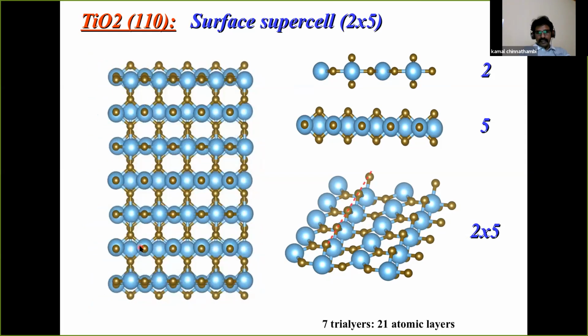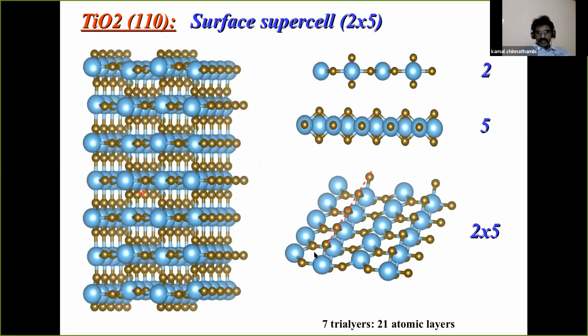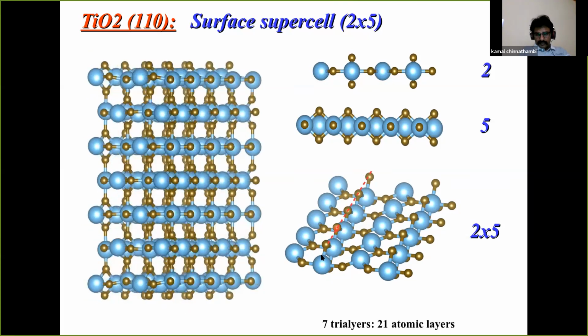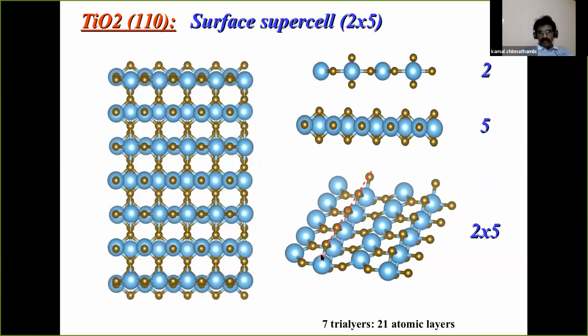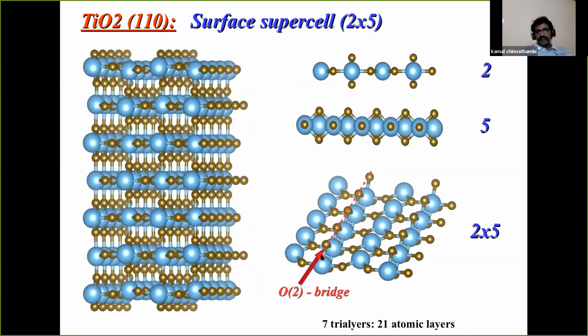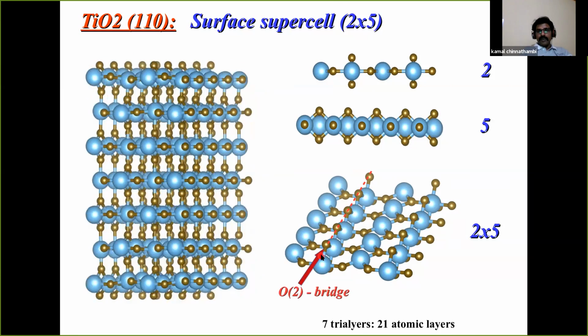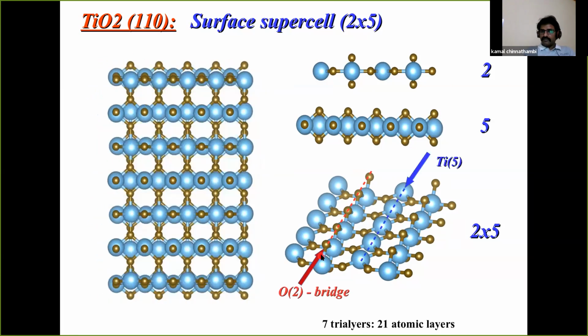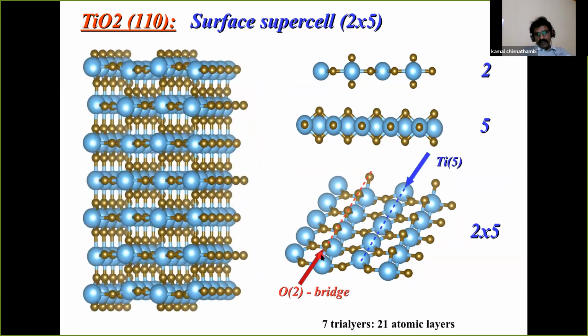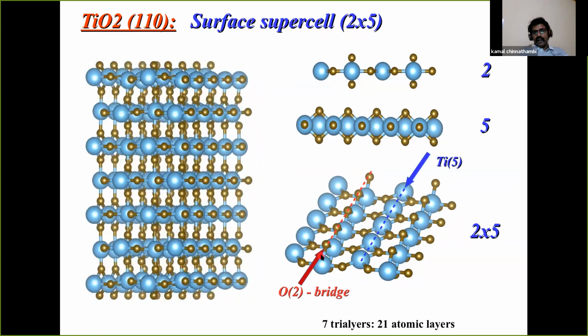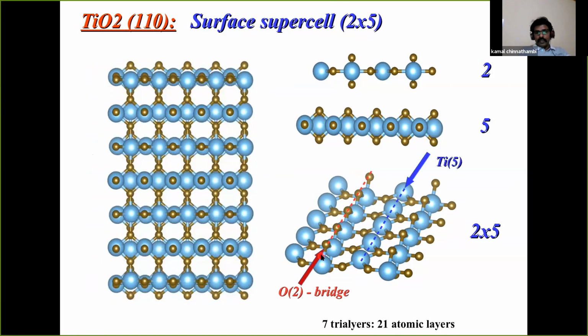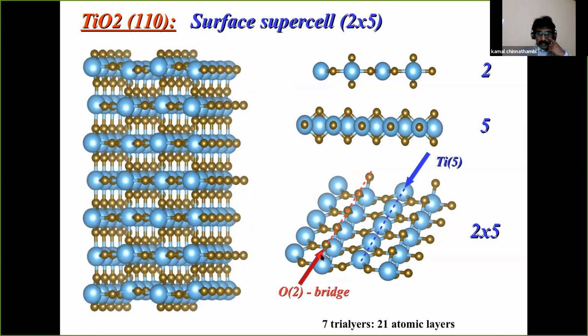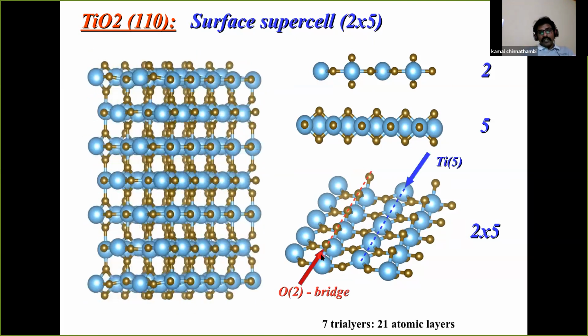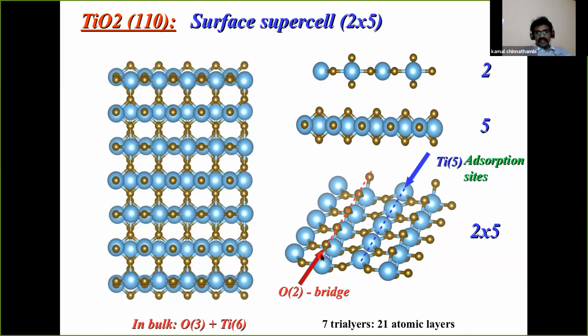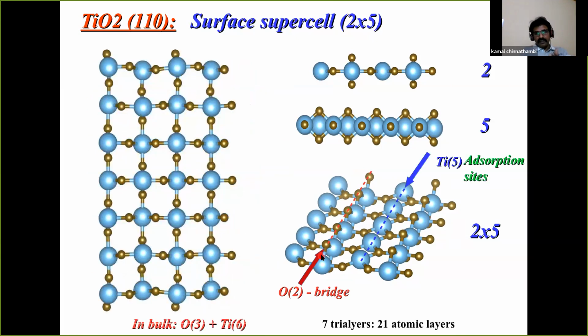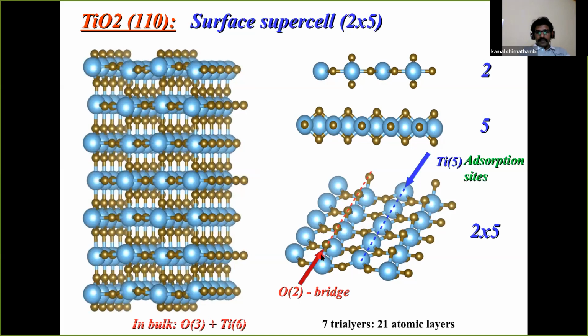On the top surface, the red arrow indicates the top oxygen atoms belonging to the titanium oxide, which are doubly coordinated. But we also have titanium which is 5-coordinated. These 5-coordinated titanium atoms act as adsorption sites for the water molecules. If you compare with the bulk, their coordinations are 3 and 6. Here, the bridging oxygen and then the titanium 5.